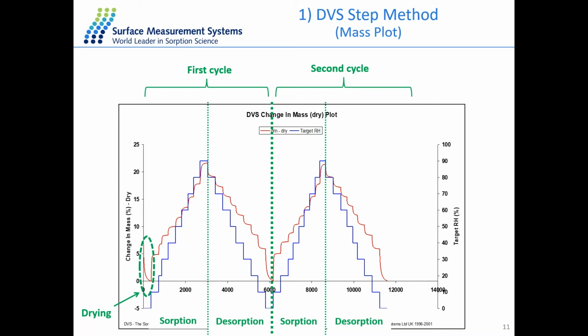There is nothing happening during this sorption and desorption. The first step is just the drying of the sample with the flow of the carrier gas. It gives you the original water content inside the sample from the mass at time zero. And this is the mass plot, the change of mass as a function of time, and it will give you some kinetics information.